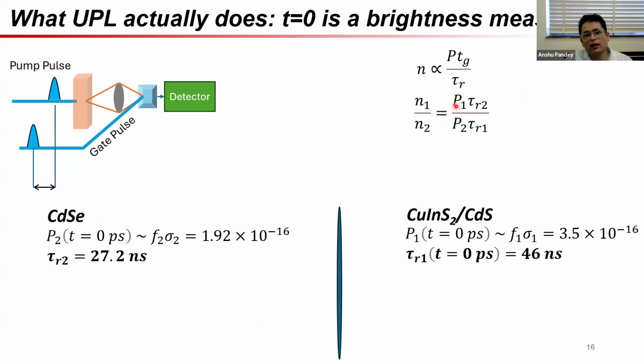Again, I'm talking about its sulfide variant, where we have coated it to make it more understandable and easy to understand. And we can take this as a ratio, because over here we end up cancelling whatever undesirables are there. What we find as a consequence is that when we take cadmium selenide and reference it, we can take the cross sections, which are very well known. And the lifetime is also very well known for cadmium selenide. This is around 27.2 nanoseconds for the sort of samples we are studying. This allows us to directly estimate, based on the signal we are getting, the lifetime for copper indium sulfide, CIS sulfide.